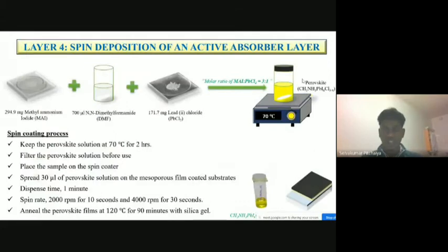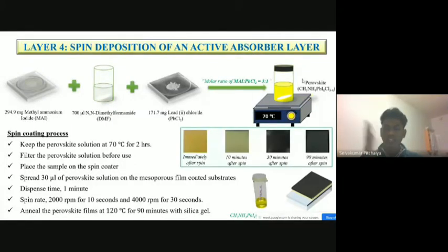This includes the active perovskite layer, where stoichiometric ratios of the precursors were taken and stirred overnight. You could see the various color changes with respect to time and temperature. After 90 minutes after spin, annealed at 80 to 120 degrees, it turns black, which confirms the formation of the perovskite structure. When it is pale yellowish in color, it is the impact of lead iodide. When it turns black, it confirms the formation of the real, phase pure perovskite structure.